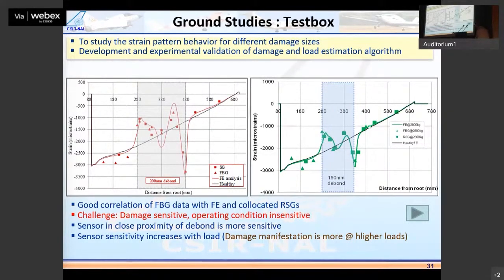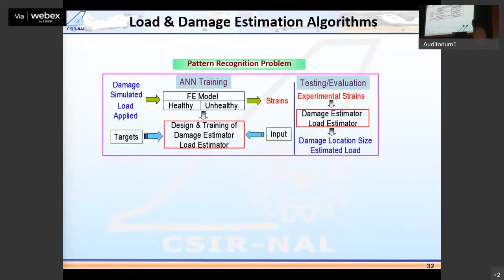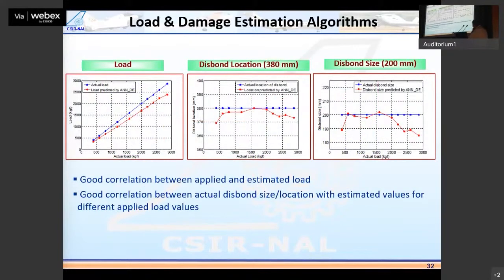And so you can see as we get closer to damage, the strain is a function of the change in stiffness, and you can see the change, and very easily we can capture that there is a damage. But one of the problems is the change in strain is very local. So this is one of the challenges. The sensors have to be close to the damage. So how do I make a network of sensors that are close enough to capture this? You can see this is the 150 mm debond, and you can easily capture the healthy versus the unhealthy. And we do this using FEM, where we create the healthy networks, we do unhealthy networks with FEM, do all the training, then build all these algorithms.